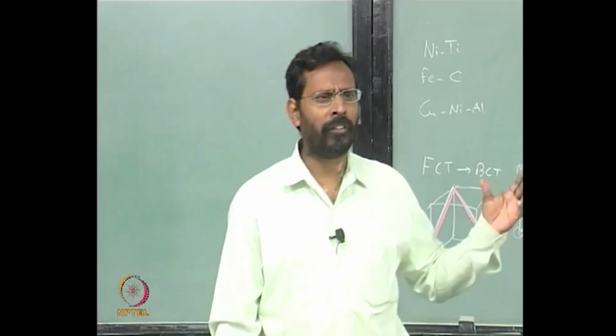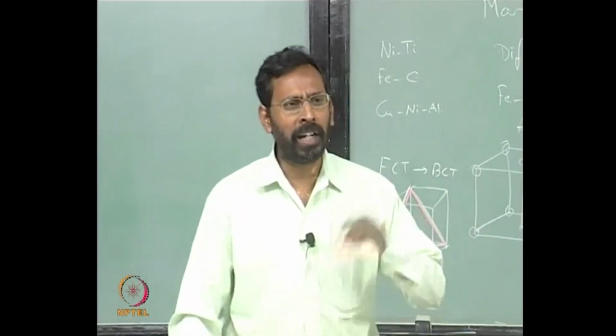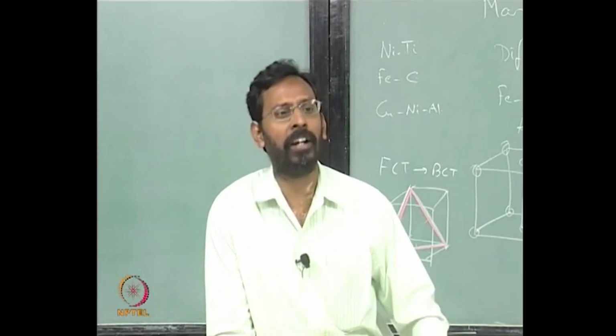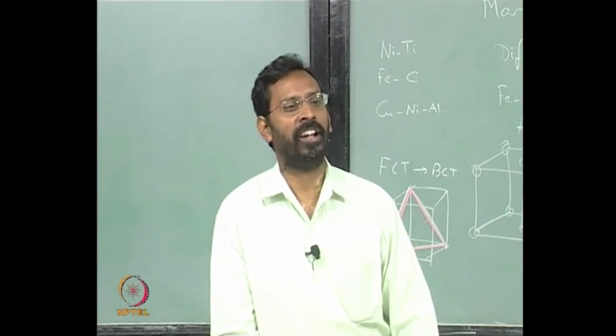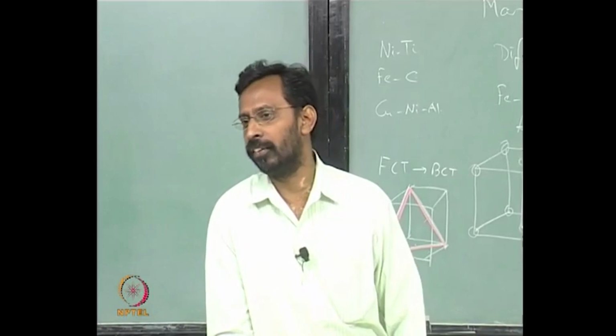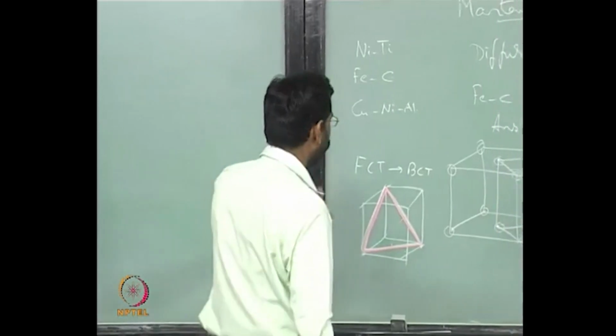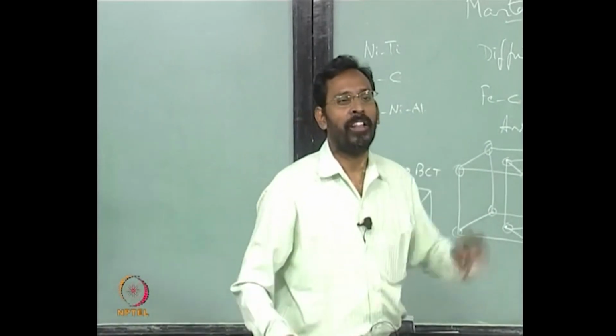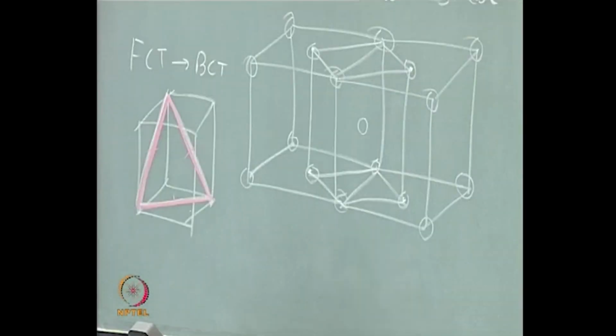So all the 111 planes have been converted into non-equilateral, isosceles triangles, and once they are isosceles triangles, obviously you do not have a 3-fold symmetry at all. The 4 3-folds that we talked about in cubic, just by pulling it by a few percent, you have destroyed the 3-fold symmetry.